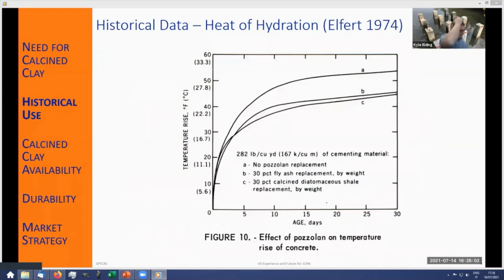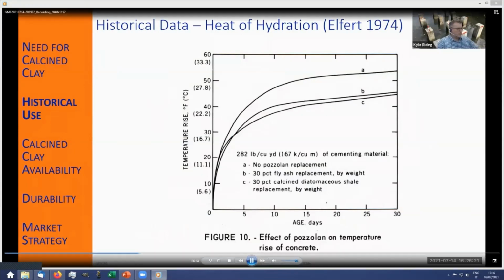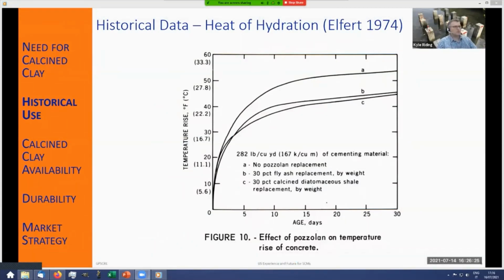When they started looking at another material, fly ash, that came to supplant calcined clay for many decades that followed, in the 50s, they actually compared it to the calcined materials' performance to show that it could give you equivalent performance to the calcined shale. And that gave people confidence that, hey, we can use this material to give us as good a performance as the calcined materials, and it is going to be useful for us. And this is how they justified the use of fly ash in the 1950s. It's ironic that it was justified by comparing it to calcined materials, because now when we're trying to reintroduce calcined materials back, we're comparing their performance to fly ash, the material that people are now familiar with.